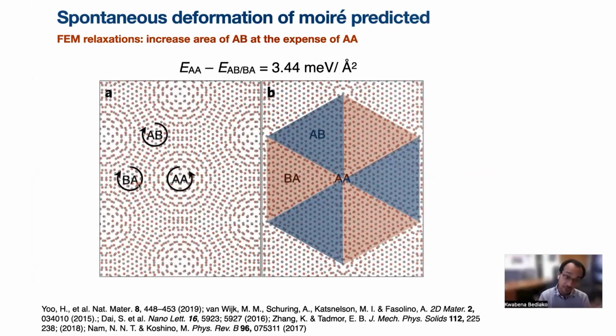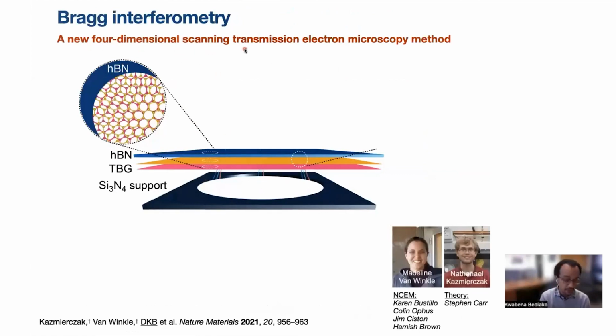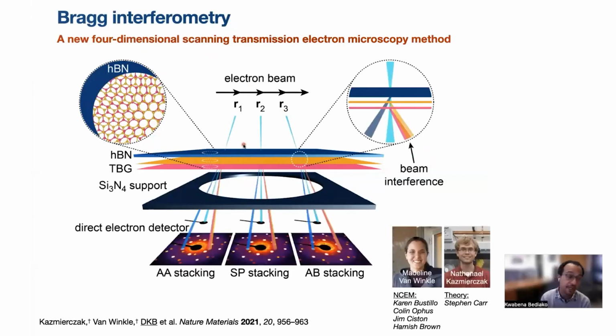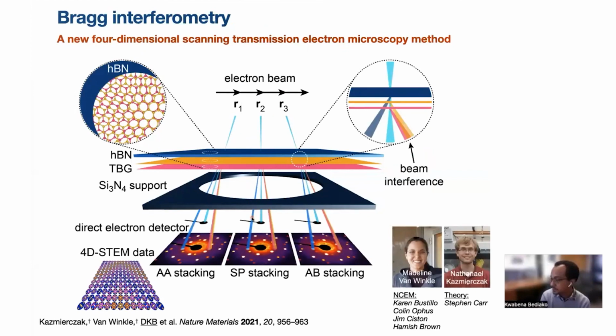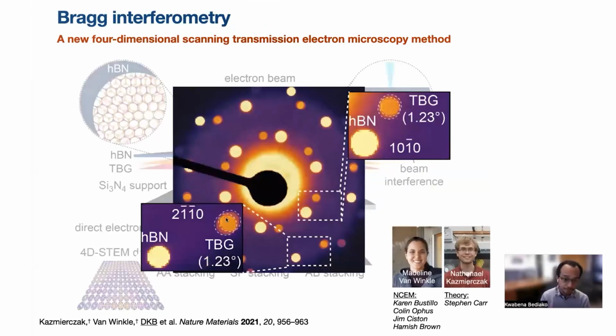And so we went ahead and did that using a technique known as 4-dimensional scanning transmission electron microscopy. What we're doing in this technique is rastering an electron beam over our sample, and at each probe position, we're acquiring a diffraction pattern, so that our 4D STEM data set is just this compilation of diffraction patterns acquired at each point in real space. What we make use of in this technique is the overlap between the Bragg disks from one graphene layer and another, and we can map that onto the local stacking orientation of the sample. Specifically, we can map that onto the displacement vector between one layer and another.